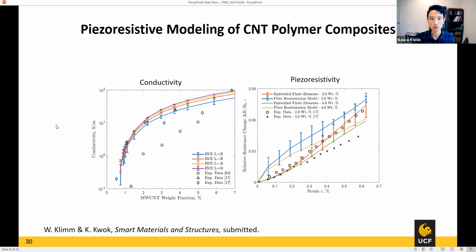This is work that we just submitted, looking at how our model can predict that strain piezoresistive response. On the left-hand side is just the total conductivity, which is a sanity check on the calculation. This is the conductivity as a function of the weight fraction, using different sizes of the RVE, and there is some experimental data in the literature. We compare our results with those data.